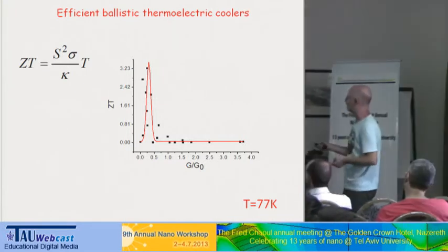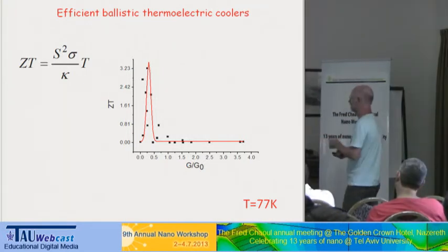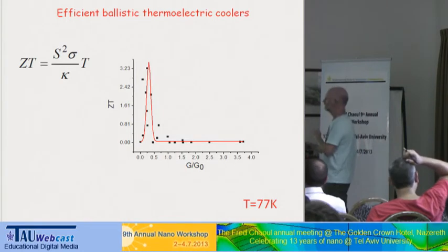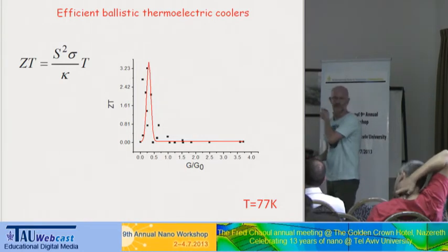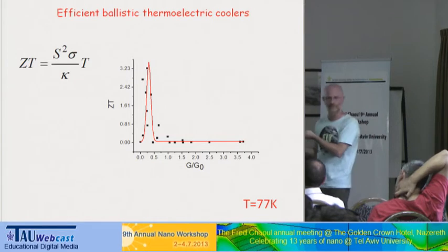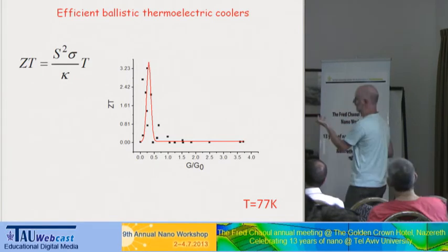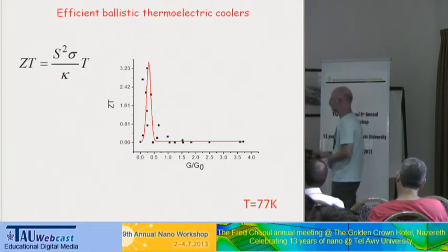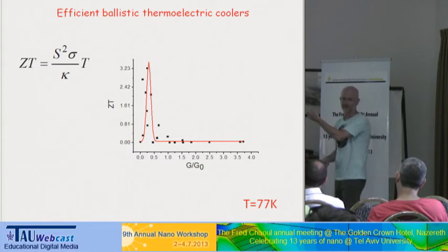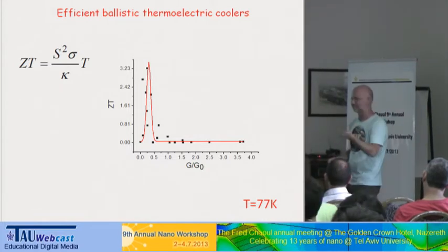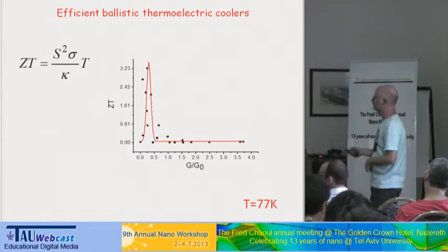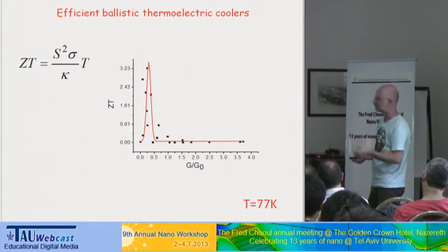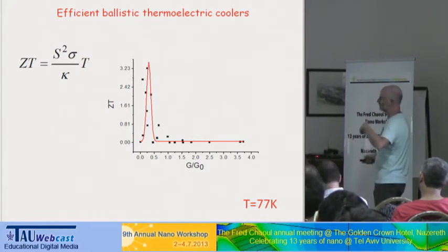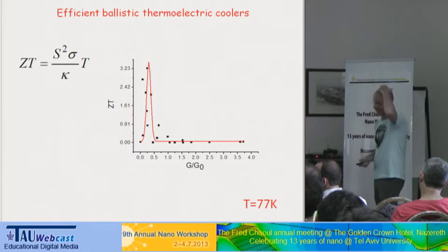I mean, we have a thermoelectric device operating at 77 K with a ZT value that is crossing 3. This has never been reported before, which I think is quite nice. The question is, how can we make it work at higher temperature? Now, at higher temperatures, you would expect that the thermal conductivity is going to be much higher, which is not good. But then, you need to remember that the Seebeck has units of entropy.